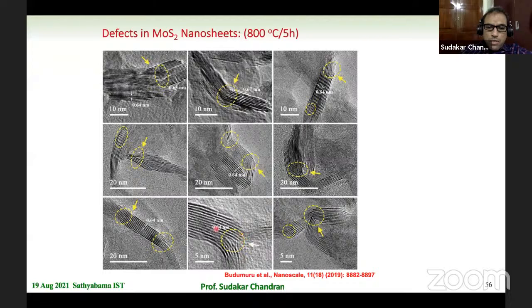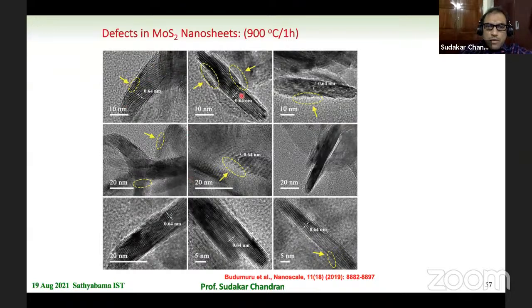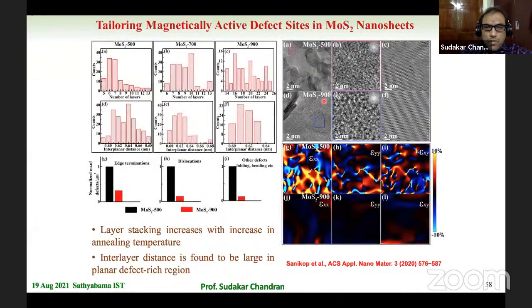For example, here too the torn part of the moly disulfide nanosheets can be seen, but slowly these get annealed out, and they become more and more straight crystals. The only defects you will see are from the edges where the planes terminate. You cannot completely get rid of these surface defects anyhow. So you can also estimate the edge terminations, dislocations, other folding and bending defects. For example, if you take a 500-degree annealed sample and a 900-degree annealed sample, you can see almost 5 to 10 times difference in these defects between the two samples. By controlling the annealing condition, you can to a large extent control these defects.